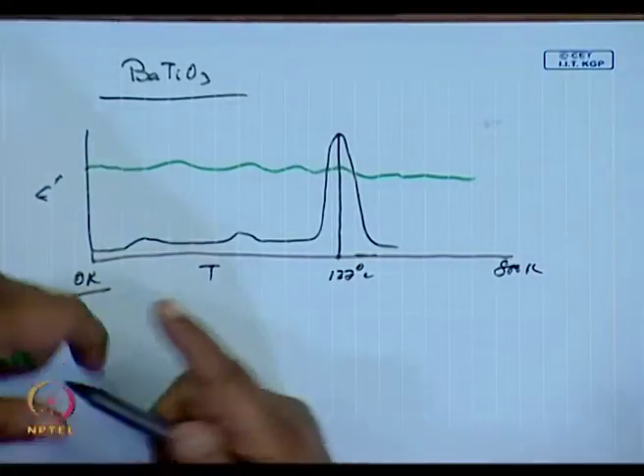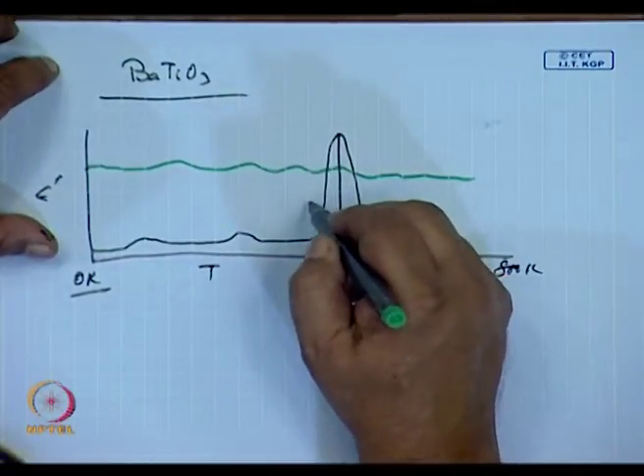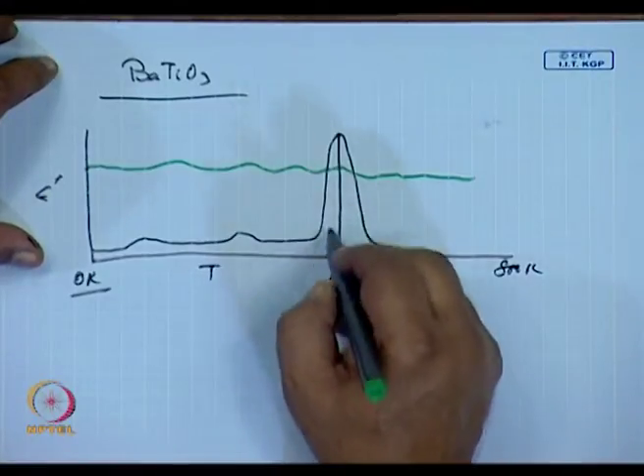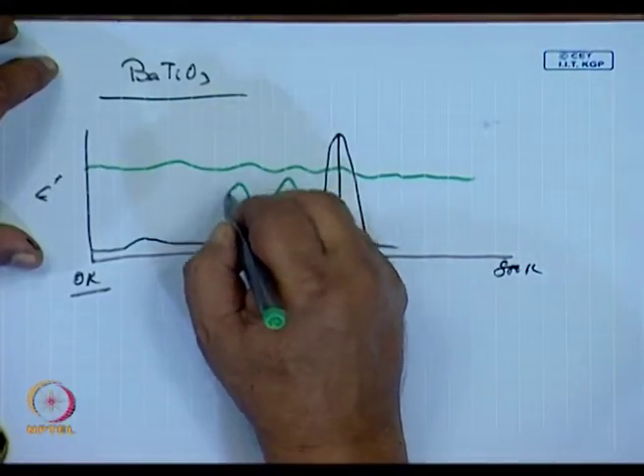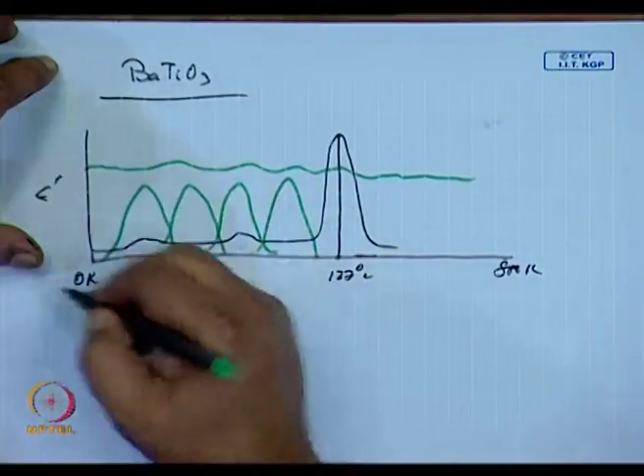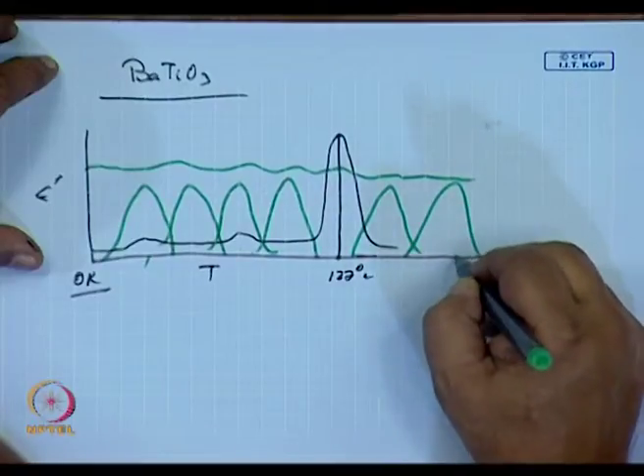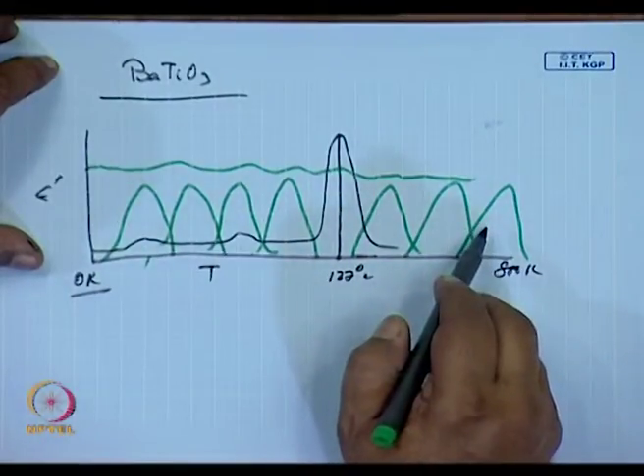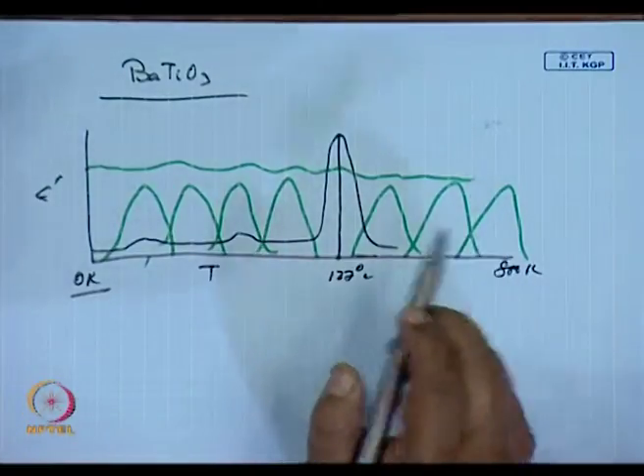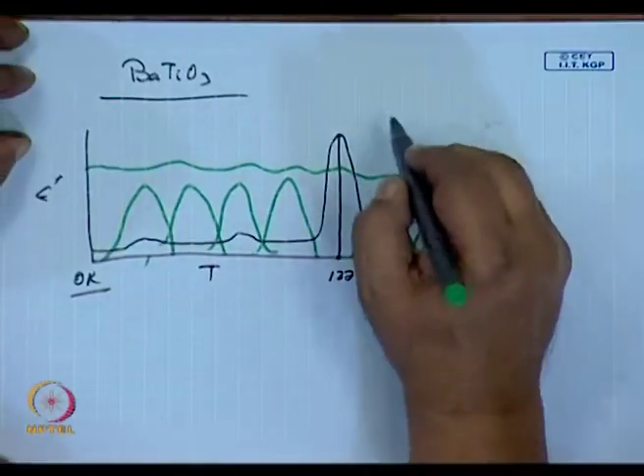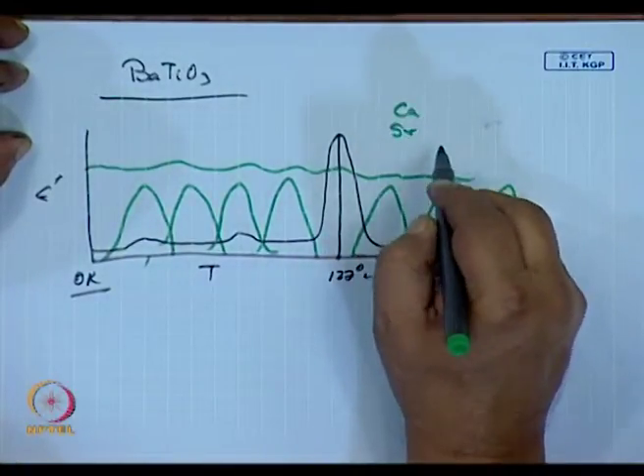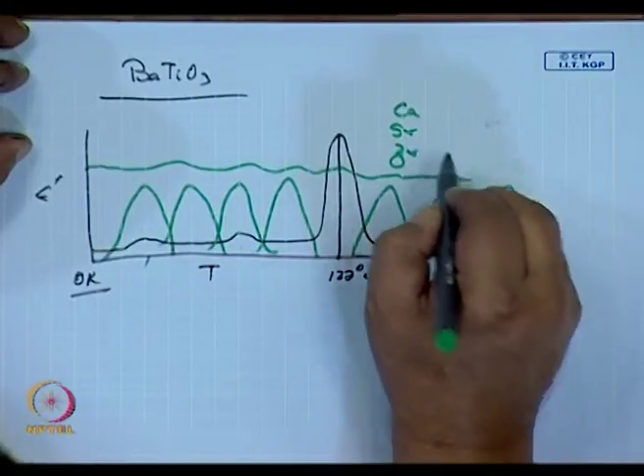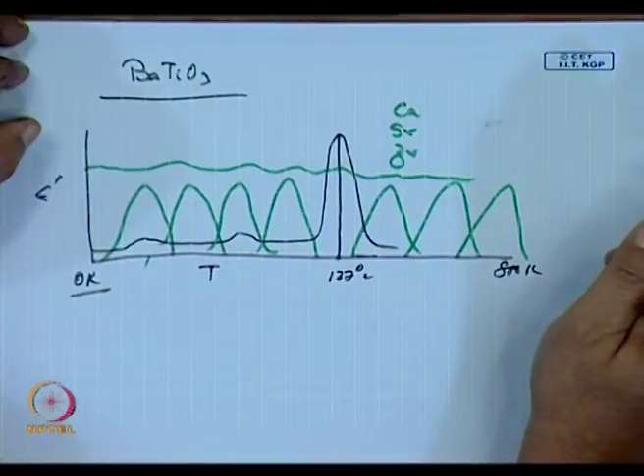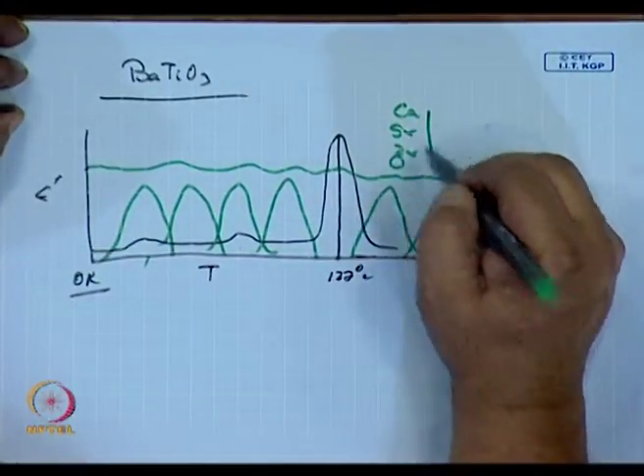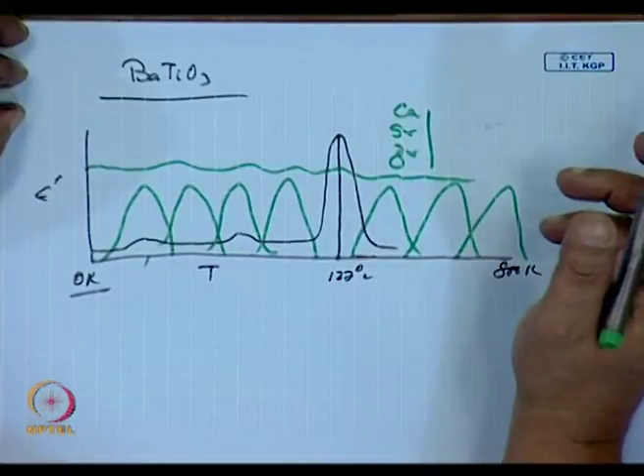So, what is done is additives are added so that they have got this Curie temperature which varies depending on the type of additive. We use various types of additives: calcium, strontium, zirconium, and a huge lot more. So, here, the amounts are very small. In some cases, we have amounts as small as 1% to 10%.